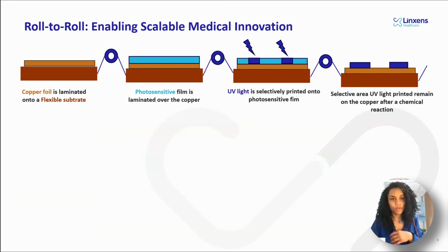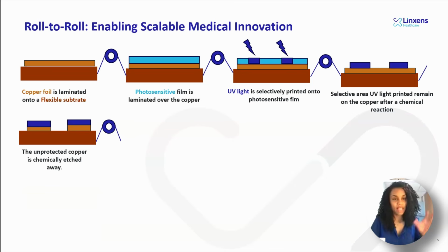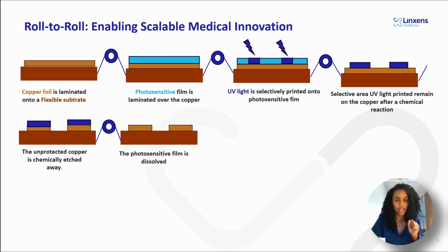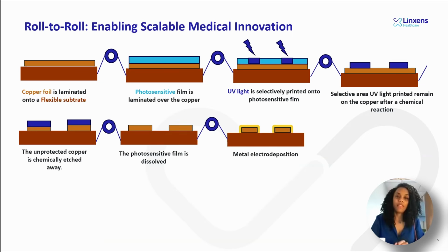So this film will cross a chemical bath, and the area where the copper is not protected will be chemically etched. After that, we will remove the photosensitive film and we will have a metal electrodeposition. And this metal electrodeposition will depend on the customer demand.